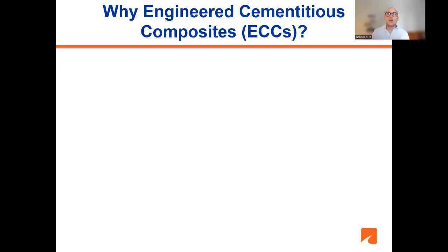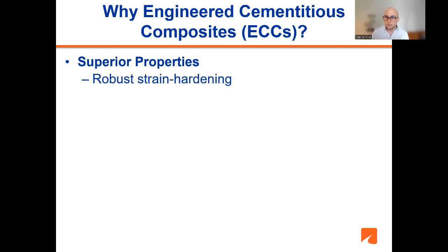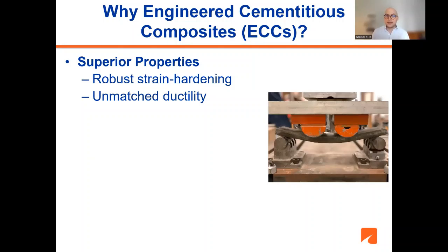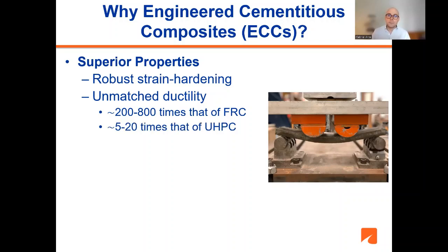So in summary, why engineered cementitious composites? First, superior mechanical properties, a robust strain hardening behavior that we talked about, and ductility unmatched by any other cementitious material. You can see this image right here, how ductile these materials are and how they can bend. And that's why usually they're regarded as bendable concrete. How much is the ductility in tension? Usually about 200 to 800 times more than that of conventional fiber reinforced concrete. And about 5 to 20 times more tensile ductility than UHPC, which is a very popular material being used in repairs recently.